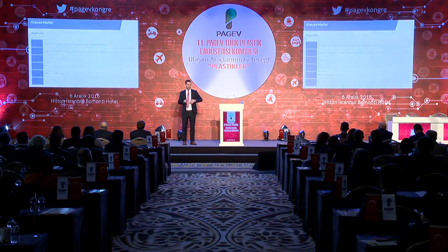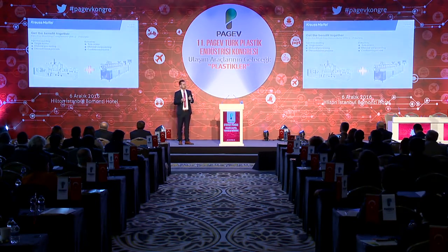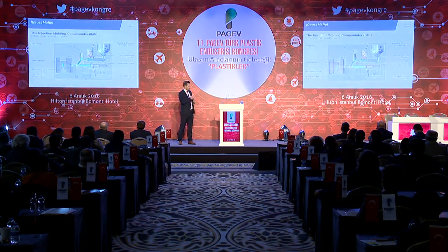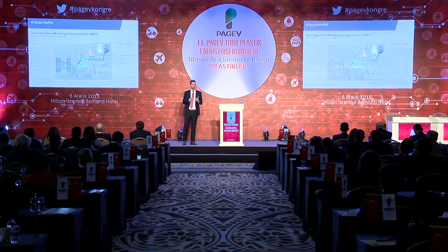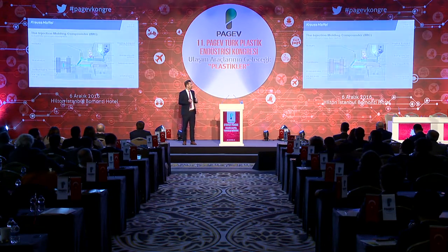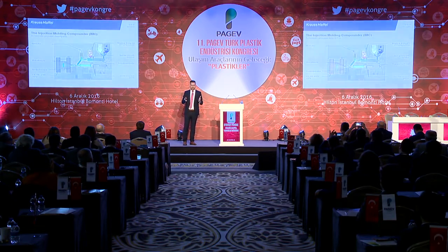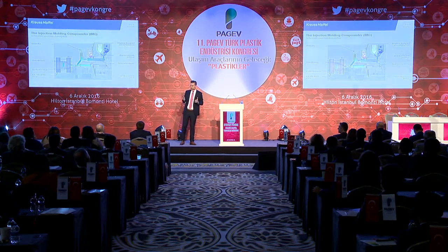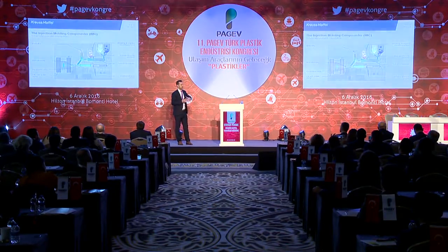Let me talk a little bit about our technology, the injection molding compounder, the IMC, which we now have for many, many years. What we do here is we combine injection molding, which is a discontinuous process, with the extrusion technology, which is a continuous process. How we do it, you can see it here. We have a twin screw extruder sitting above an injection piston, and we basically do this for saving material costs. If you process such a fiber-reinforced pelleted material with 8 or 12 millimeter in length, that costs a bit of money. And if you directly process fibers and plastic material inline in your process, you are able to save money on the material cost side. Of course, this technology is a bit more complex than easy injection molding, but in the end, it really trades off.